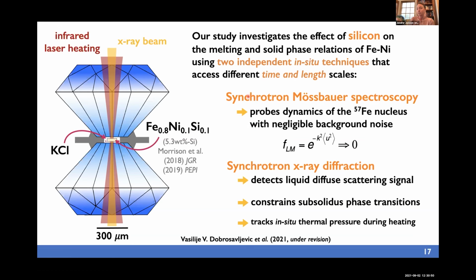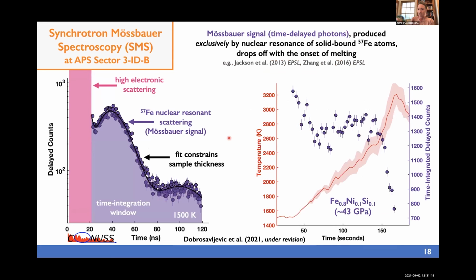This combines two techniques: synchrotron Mössbauer spectroscopy, which I've been developing with colleagues at Sector 3 at the APS, which probes the dynamics of the iron-57 containing atoms in the sample, and synchrotron X-ray diffraction. So these probe two different time and length scales. In this example, we show the synchrotron Mössbauer time spectrum, which constrains the thickness of the sample, which is important, and the integrated time delay as a function of temperature.